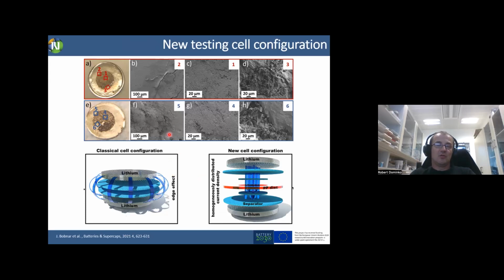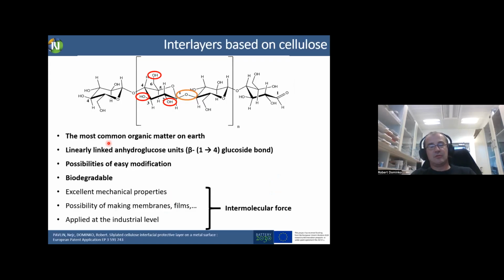And then looking at both electrodes, we see that this protective layer didn't have any function, because it seems that the polymer didn't sustain the cracking, and then we can observe the formation of high surface area lithium. But that's a nice example of how the community has to be aware and experiment carefully, and that gave us also a nice tool for continuation of this work. And in continuation of our work, we moved to cellulose.